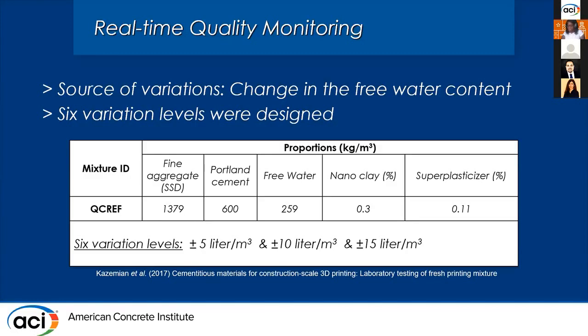And I should say plus minus 10 is usually the number that is used for variations that we have in conventional construction. For example, for self-compacting concrete, we usually use plus minus 10 as the amount of variation that we should be able to deal with. So I added 5 and 15 so that I can have a good idea of the performance of each technique against different levels of variation.